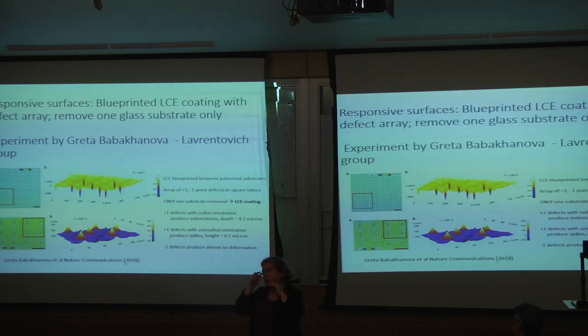So for instance, if you take one of these light responsive materials, you can have a thin film mounted on the bottom with a uniform nematic director. This is an experiment by Tim White. And you shine the laser from this side, and it will bend down. And then the other side is in the light, so it'll bend up and it'll oscillate at hundreds of hertz. Okay, so momentum's not conserved.